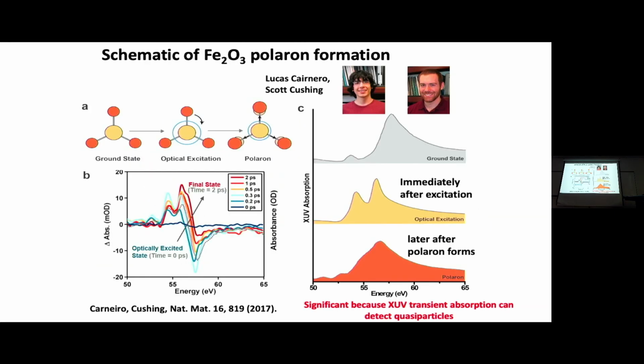And so Scott Cushing, who's now on the faculty at Caltech, worked out what would be the spectrum of the ground state, what would be the spectrum immediately after excitation, and what would be the spectrum if a polaron forms. And he showed very exactly that this was the process that was happening, and even the amount of the polaron, what fraction was polaron, and so on. And so why this is significant is, in addition to detecting that we saw the charge transfer, we're also saying we can detect quasi-particles.